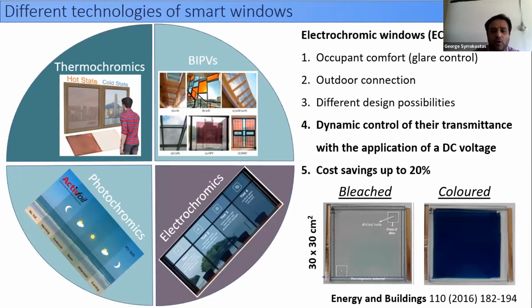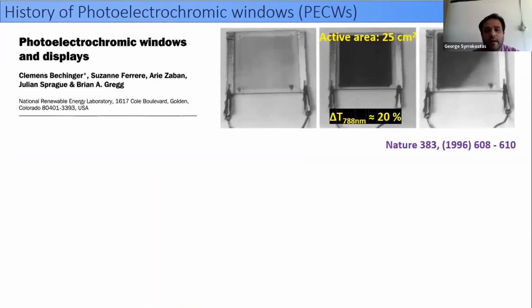So these photoelectrochromic windows have a dual behavior. On the one hand, they can generate energy, and on the other hand, deliver a smart optical response. Therefore, as we will see, they combine a PV unit with an electrochromic unit in one unified device. The first appearance of photoelectrochromic windows was nearly 25 years ago in Nature, where a photoelectrochromic window with an active area of 25 square centimeters achieved an optical modulation of 20% in less than 2 minutes.